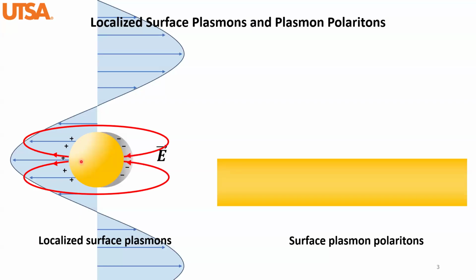In this case, if you take a look at the local electric field that is generated by this free electron oscillation, you have negative charges on the right side, positive charges on the left side. So the electric field actually points from the positive to negative, in the dielectric, right? If you take a closer look at this area, the electric field that is generated by the surface plasmons is in the same direction as the external field. So it causes some optical enhancement in the very close vicinity of the nanoparticles. And this enhancement can reach tens or hundreds of times in intensity.